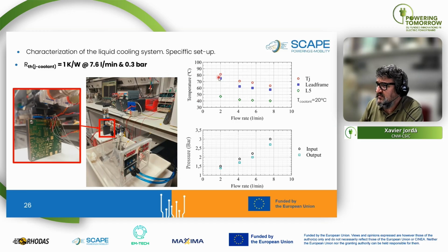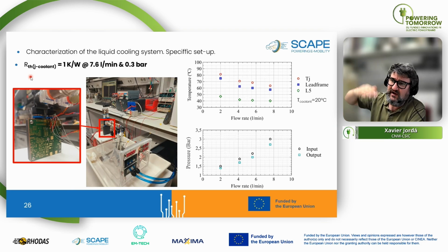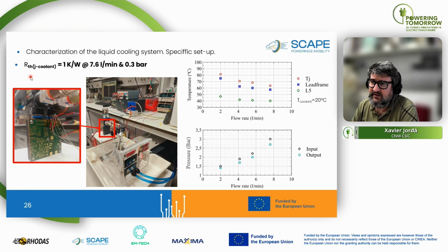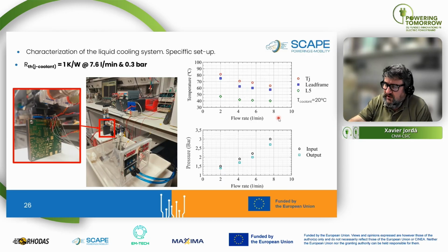Then you can see that we have this response increasing the flow rate of the coolant with this pressure drop. And you can derive from this that all this information translates into a thermal resistance between junction and coolant of around 1 Kelvin per watt at 7.6 liters per minute. This is a good figure for taking into account the nominal power at which this switching cell is designed.